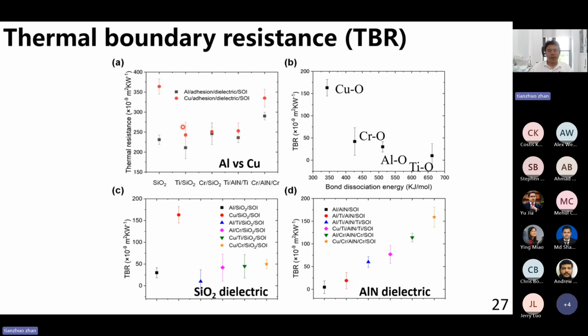And so we also calculate the thermal boundary resistance of these heat spreader layers. We found that even though aluminum has a lower thermal conductivity than copper, the sample with the aluminum layer has a lower thermal boundary resistance, so it results in better performance. And therefore, aluminum is better than copper as the metal layer in the heat spreader layer.